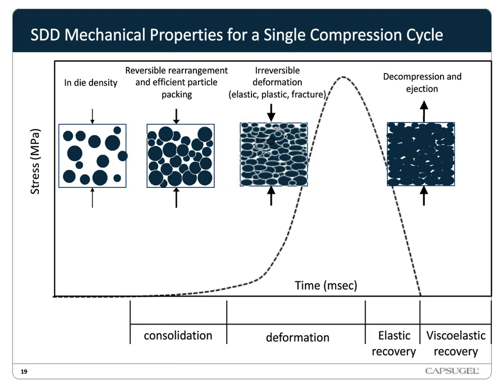Now, particles can deform elastically, plastically, or they can fracture. For SDDs, this is dependent on the material. As particles deform, there is an increase in the proximity of particle surfaces, forming bonds. So generally, the higher the true area of contact, the higher the strength of the compact or tablet that is made.